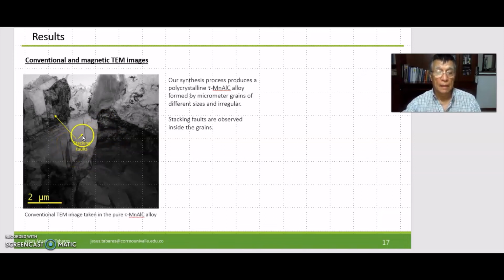Inside some grains, we observe stacking faults and crystal defects that have probably been created during the epsilon to tau manganese aluminum carbon transformation.